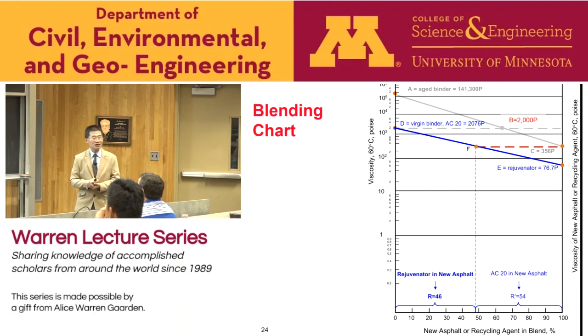And a blending chart was used to determine the required grade of the recycling agent. The target viscosity we used was 2,000 poises at 60 degrees Celsius. So that's a control point for all the blended asphalt used in the mixtures. That's very important. We use 2,000 here for the control point.